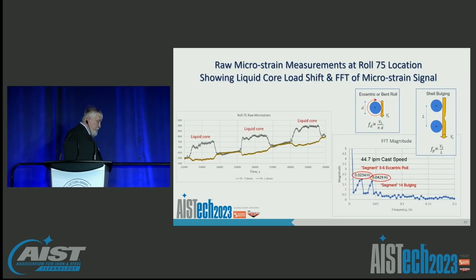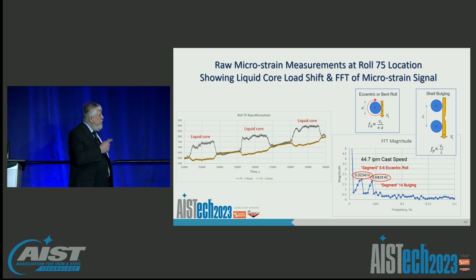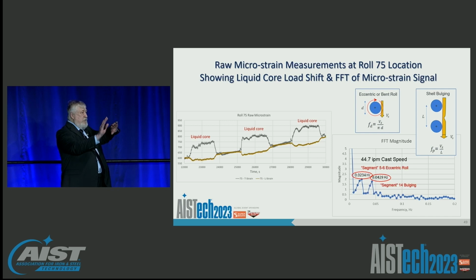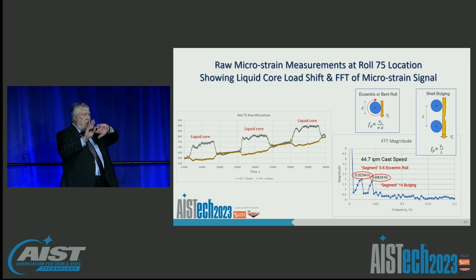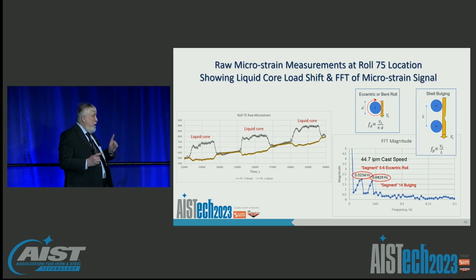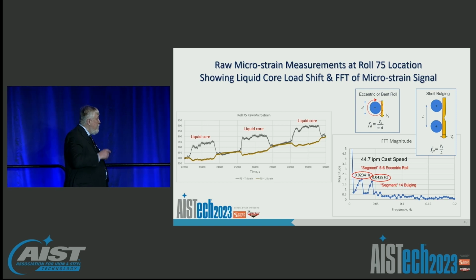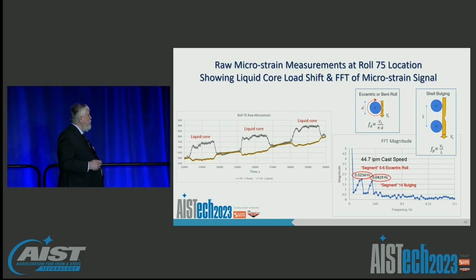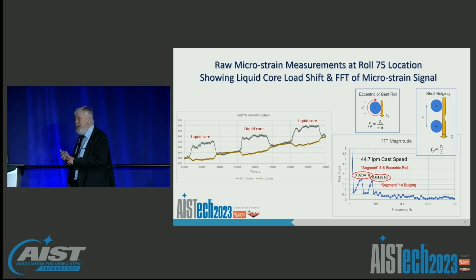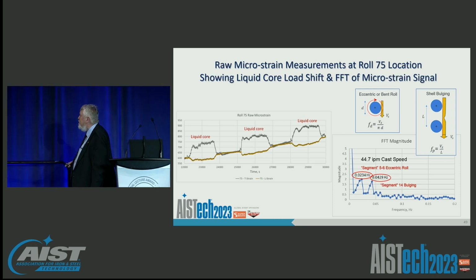The other thing about these fibers is that they're pretty sensitive. We can see what looks like noise in some of these fibers. And you'll notice we have two signals. We, in this case, used FBGs mounted longitudinally and transverse, such that when the roll force imparts deflection to the beam, we see a positive increase in the longitudinal direction, but a negative due to Poisson's ratio of the beam. And so it's really easy to separate temperature and strain doing that. But the signal and noise on that individual signal can also be separated out. And in the frequency domain, we've been able to show that you can actually see bulging and bent roll conditions in the machine using these sensor technology.